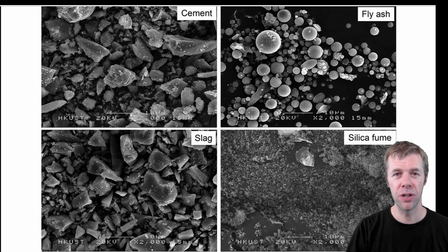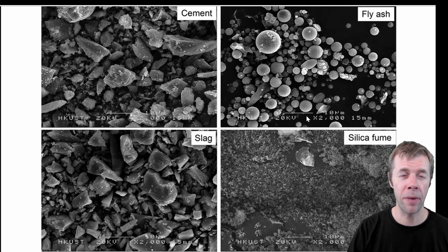This is an image from a scanning electron microscope of the three SCMs that we've just been talking about compared to Portland cement. Now, in all of these, the scale bar is exactly the same, 10 microns, okay? That's 1/5 the size of a human hair. We can see our fly ash particles. I said they were spherical. You can see them right here. And here is Portland cement. Much more oval-shaped, angular, long-shaped particles. And they're about the same size. And we have slag particles down here. They're a little bit different shape than Portland cement. They have a a similar size distribution.